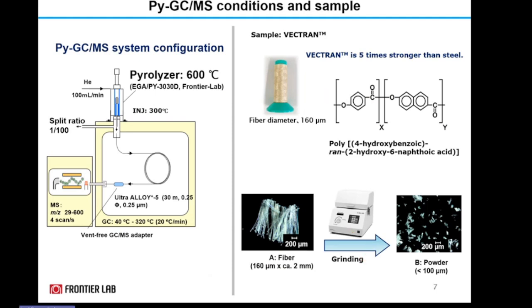As you know, we are more into this pyrolysis GCMS application. So we have taken an example to show how this crushing mill really helped to improve the data quality by this PY-GCMS. We have taken a sample which is called Vectran. It's basically a poly-4-hydroxybenzoic acid, like hydroxynaphthoic acid. But in terms of its strength, it is 5 times stronger than steel. It comes as a fiber-like material. So after grinding, you see them as a kind of powder, which has a particle size less than 100 micron.